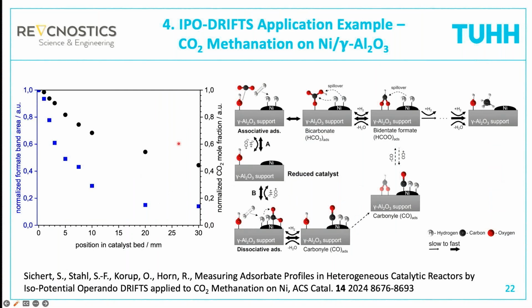But nevertheless, you see that the principle works, and we can now interpret this mechanistically. I don't want to spend too much time, but you see here there is a close correlation between the normalized formate band intensity and the normalized CO2 mole fraction, and that points towards the formate being the catalytically relevant intermediate here in the CO2 reduction. So we basically follow the associative mechanism.